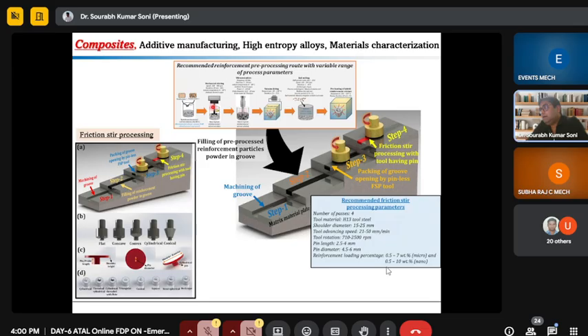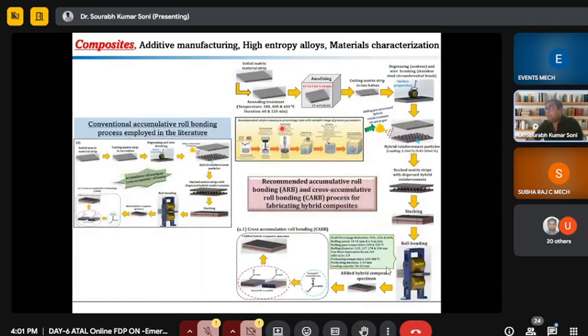After reviewing the literature, I recommended this route for FSP processing, so we can get very good properties in the resulting composites. So first, before filling the hybrid reinforcement in the groove, we can pre-disperse the reinforcement, and then we can do the FSP with the recommended FSP process parameters. So we'll get composite with good properties.